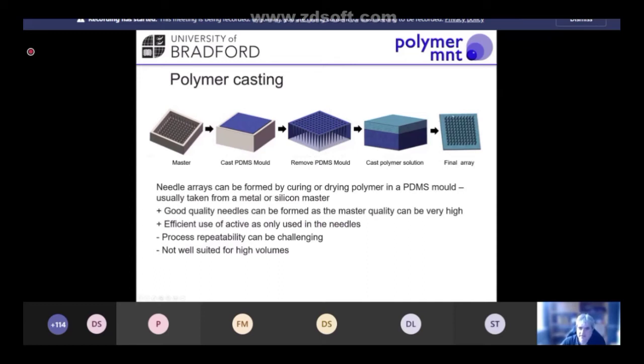Some of the advantages are that you can minimize the amount of material that actually contains the active pharmaceutical ingredient, because by controlling the volume dose here, you can make sure that you pretty much only fill the cavities in this mold. You can then apply a backing plate onto that that has no active pharmaceutical in it, and that minimizes your wastage of your drug for the given application. So if the master quality is really good and you get excellent replication of your PDMS mold, you can get very good needle structures, but you have to be careful with the process, and you normally use pressure or vacuum to enable this to occur.